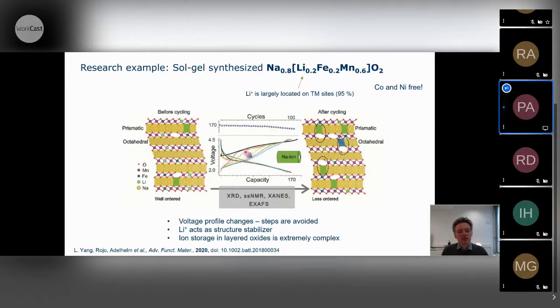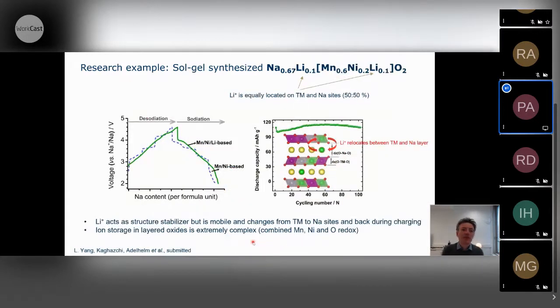And as you can see here from the voltage profile, we don't have this staircase behavior anymore, so we have a sloping behavior. There's also a voltage fade and so on, so not everything is perfect. But you can see that by changing the stoichiometry of these transition metals and by adding elements like lithium or even magnesium, you can stabilize certain structures. Overall, however, the whole process of storing ions in these compounds is extremely complex. So you need many methods to study these materials, and still, even though you apply a lot of methods, very often it's not clear what really happens.